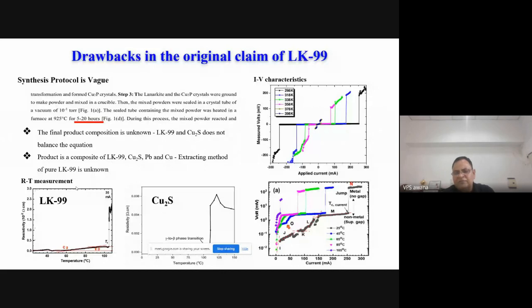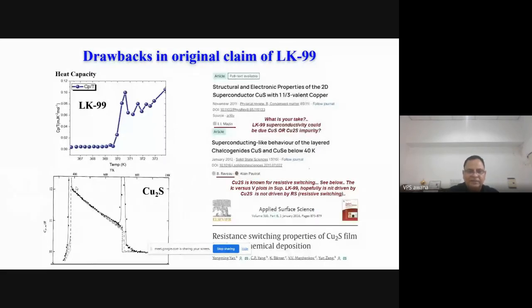It's a kind of switching of the resistance, and this actually persuaded me to put on my Facebook after I did see some papers that will come in the next slide. I looked at copper(I) sulfide and could find that this is exactly the behavior of that one. LK-99, if we look at their graph, it comes from 100 Kelvin, above 100 degrees centigrade. There is a transition from insulator to metal, but it is not R equal to 0 even at a later stage. And if you see the copper sulfide literature, there is a gamma to beta phase transition exactly at the same temperature, and copper sulfide actually goes from insulator to a metal type of transition.